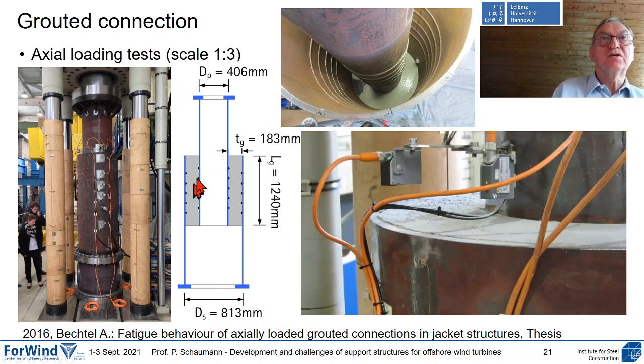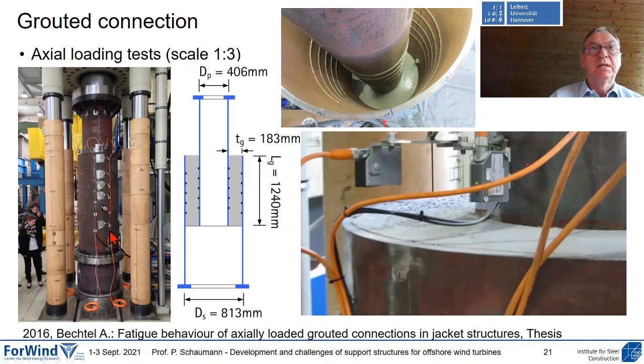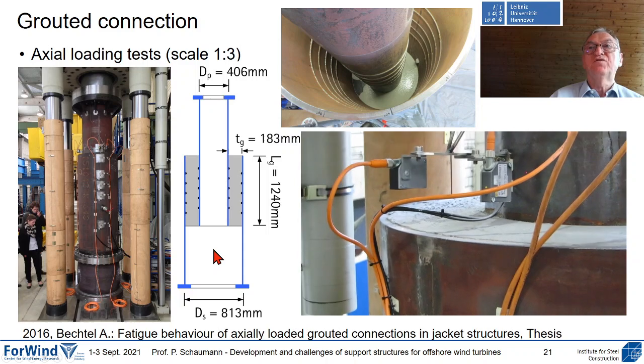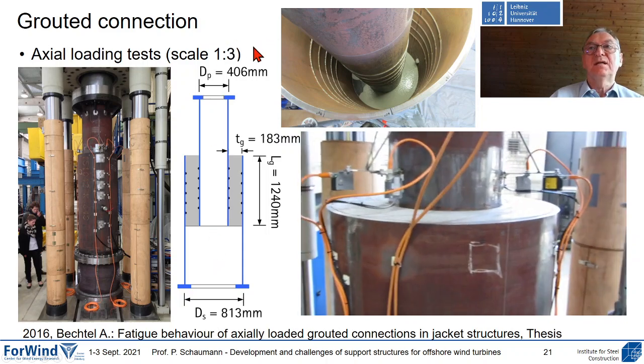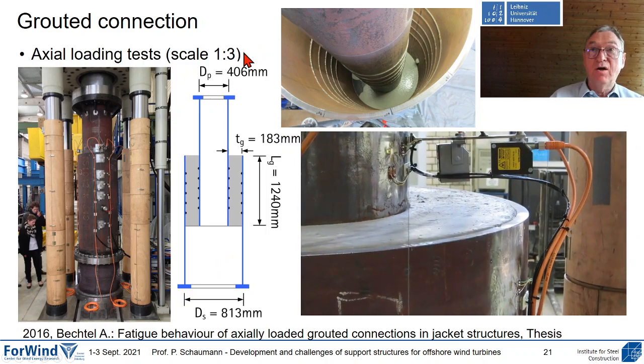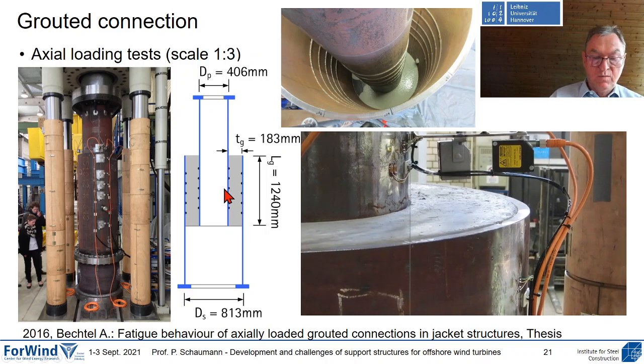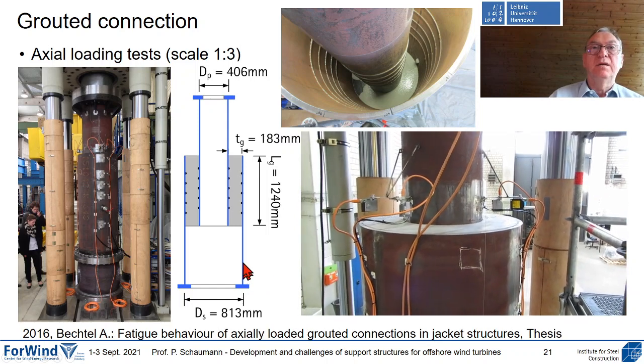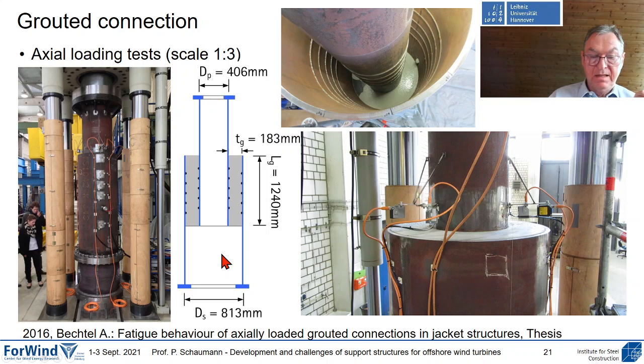And then we started investigations on actual loaded grouted connections, which is typically the situation when you have jacket constructions. First of all, we tested them in dry conditions and developed a design method for that. And one of the things we learned from that project was that the model of a uniform longitudinal shear was obviously wrong. In this case, we have no uniform shear distribution in these shear keys, but the outer shear key connections have much more load than the inner ones. So we have to investigate a non-uniform loading of the shear keys with appropriate finite element models.